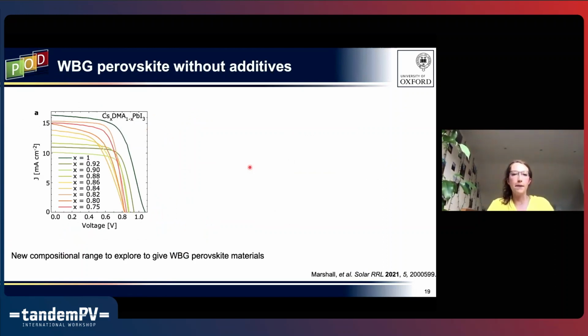So one thing to end on before I conclude is looking at wide bandgap perovskites without any additives yet. They'll probably be coming very soon. But my project focuses on the inorganic perovskites. So instead of starting from mostly FA, starting from mostly cesium, and in this case, adding in dimethyl ammonium in order to stabilize the cesium lead iodide material. You see a bit of a VOC drop by adding the dimethyl ammonium. This drops the band gap just slightly, but we see a bit more of a VOC loss than maybe we would expect from just a band gap change. And in this case, we think that's maybe a material quality issue.